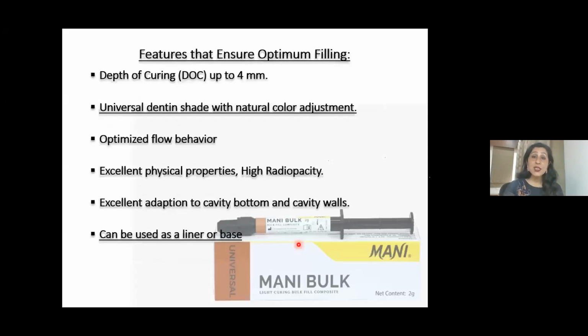Have you ever thought about why you can use bulk composites in a 4 millimeter increment? It is because they are translucent. And because they are translucent, they permit the light energy to go into the deepest layers also, so that there is generation of free radicals and there is polymerization. So when you have a 4 mm increment in a translucent shade, and if you want to give an aesthetic result, then you will top it up with a Mani Micro or a Mani Nano. Otherwise, you can leave it as it is.